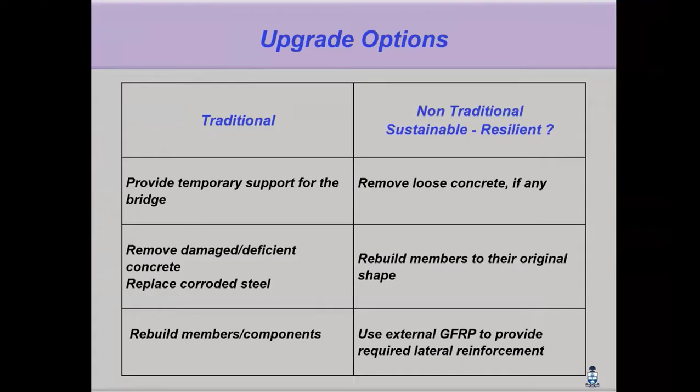Now, after this, they have never asked me a question about the validity of this procedure. And now they're telling us that this really was a milestone in their repair method, simply because after 25 years, they didn't need any interruption or any interference. Whereas any other normal traditional retrofit techniques had to be redone every 8 years on average. So they found this to be quite nice. The second issue was, when I showed you the traditional method and this method, if $1 million was needed for the traditional method, we only needed between $100,000 and $200,000. So, there was a saving of at least 80% in following this procedure.